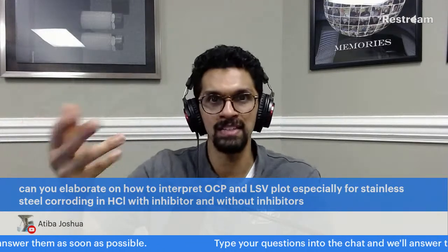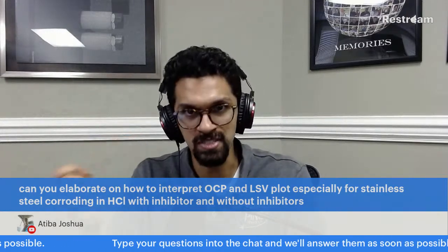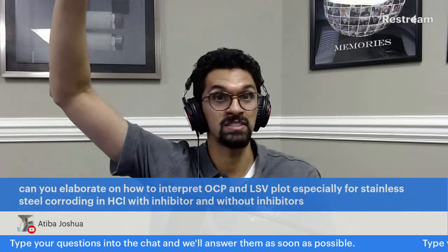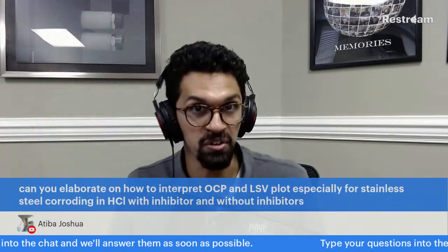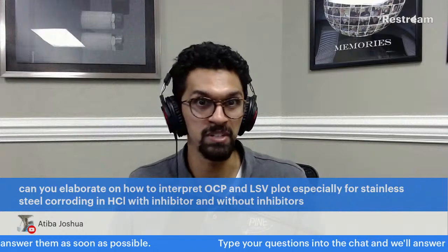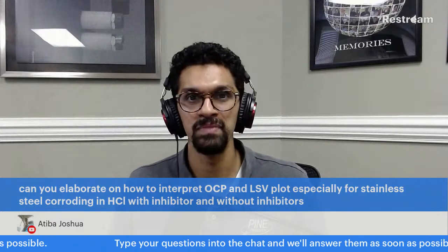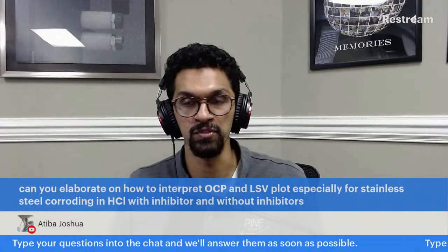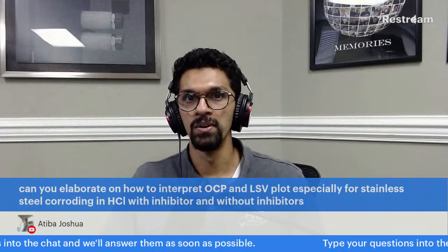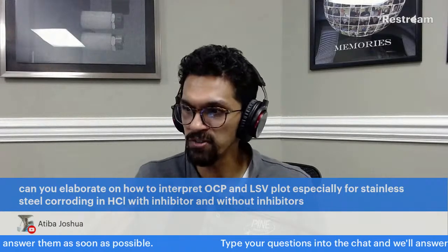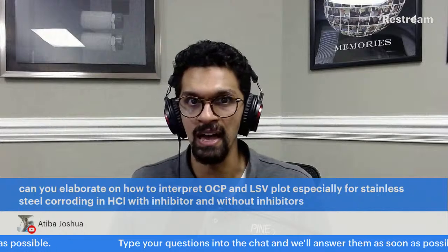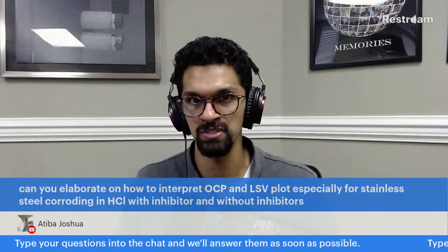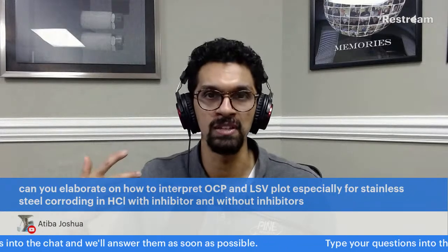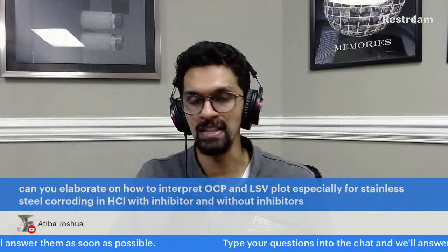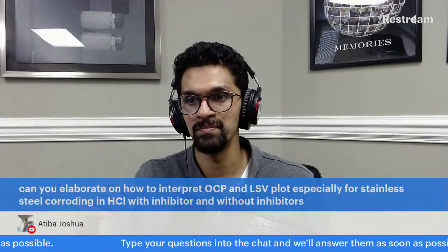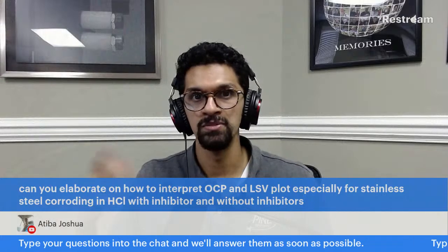And then when you add the inhibitor, because you're measuring the resistance, you see a resistance value that starts to skyrocket, where the current versus the potential, you have much, much less current for the same amount of potential. So instead of OCP and LSV, you're really looking at this linear polarization resistance, and you need to put in some information like the density and the Tafel slopes. You need some of that information.